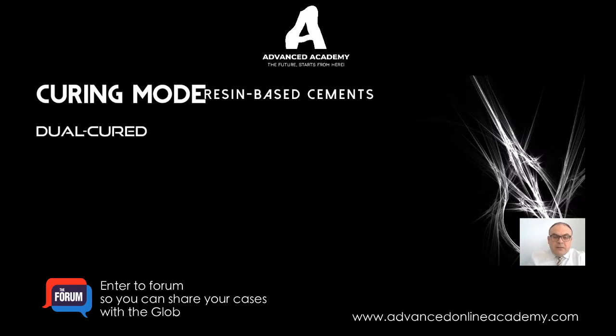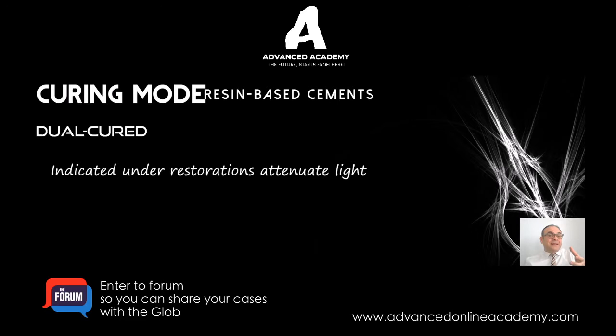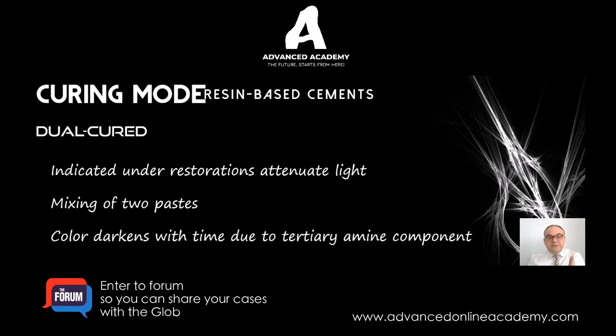And so the third type of the cements that we have is the dual cure cements. Now, these are indicated under restorations that can attenuate light. When you have a restoration that you think light passage is limited, but it does pass, but not fully, then I would consider using a dual cure cement. It's also two pastes, and also the color darkens with time due to the tertiary amine component. This is a light cure and a chemical cure component that are combined together. The chemical cure component has the tertiary amine in it. So therefore, it is going to change in color with time also.